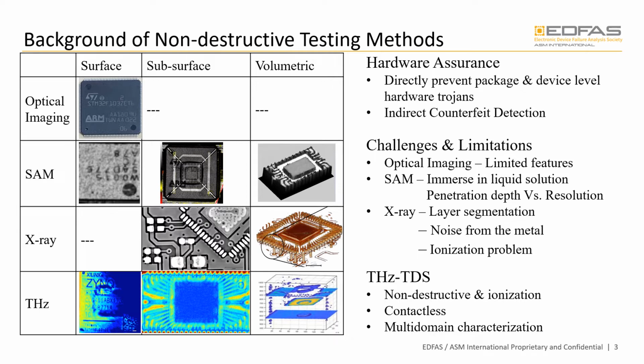Second, we have the scanning acoustic microscopy, and this can both characterize surface as well as subsurface information. It's mainly used for failure analysis purposes, and it can identify voids, delaminations, and cracks, etc. So for hardware assurance, it is able to detect extra bond wires, different lead frames, or different IC shapes. The only downside with scanning acoustic microscopy is that it requires the sample to be submerged into a liquid, usually water, and this can lead to sample damage and inefficiency.